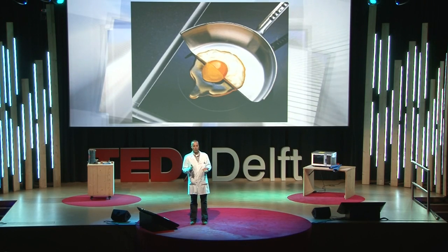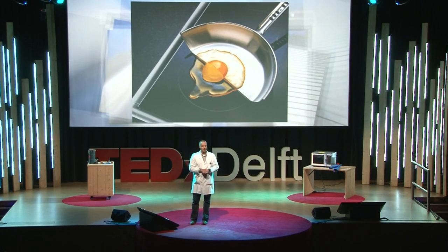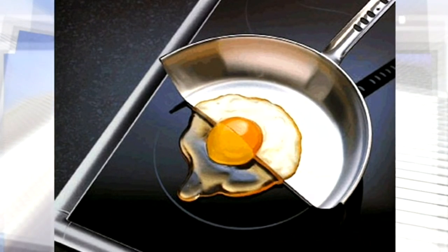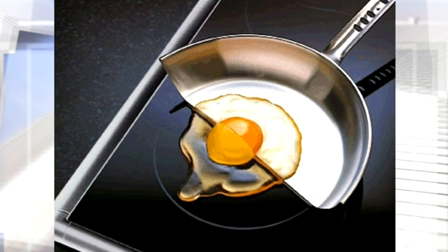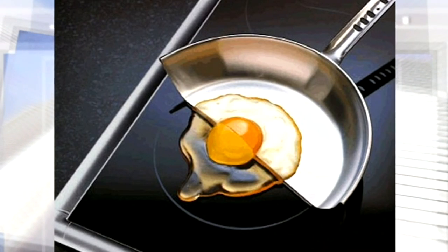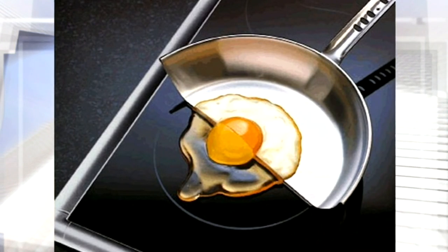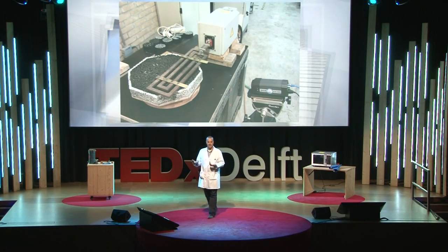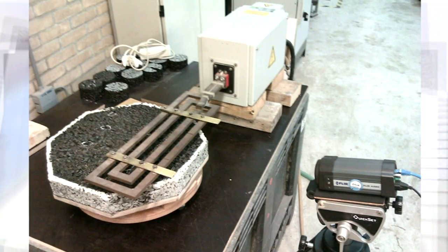Then you need a machine like you see here that you can use for cooking, an induction machine. Induction can heat, especially steel, very well. Then you heat up the steel, you melt the bitumen, and the bitumen will flow into these micro cracks, and the stones are again fixed to the surface. Today I use a microwave because I cannot take the big induction machine on the stage, so a microwave is a similar system. So I put the specimen in, which I'm now going to take out to see what happened.